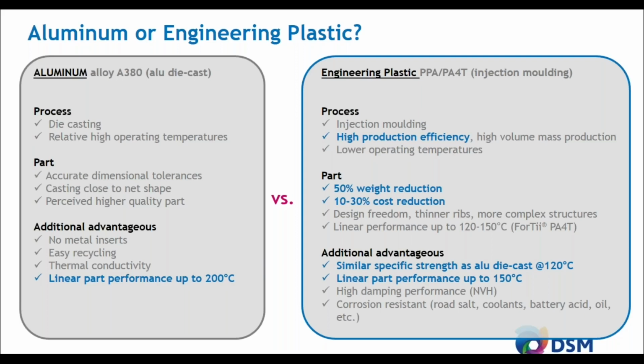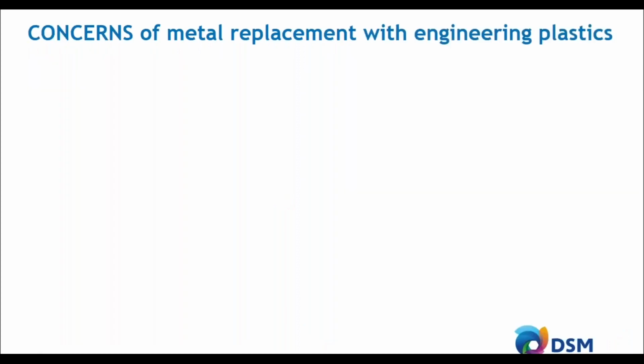But what about the part performance? What about the temperatures to be achieved? With PPAs, you can push the boundaries, and we see that PPAs could be really the next best alternative to aluminum. With glass transition temperatures up to 150, 160 degrees C, we see that these materials can be used and are as strong as aluminum up to around 120 degrees C.